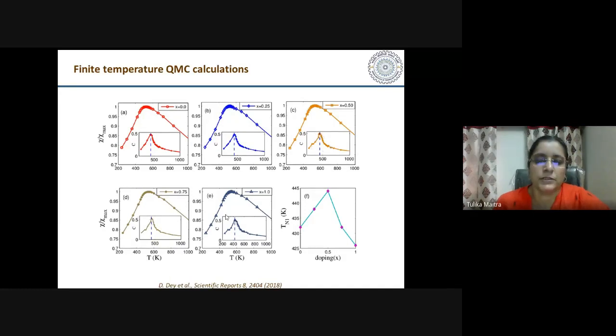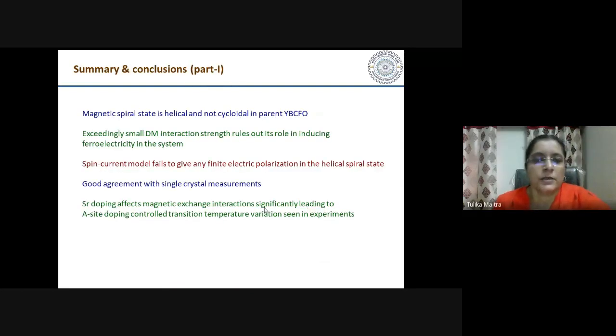varies with the doping. This plot shows how this TN1 varies with doping, and we see that up to 0.5 it increases and then it decreases. So these are some of the conclusions that we make from our study.